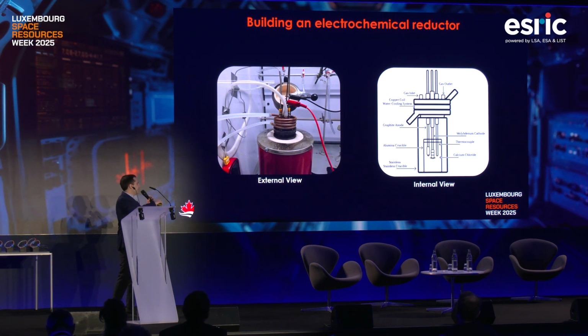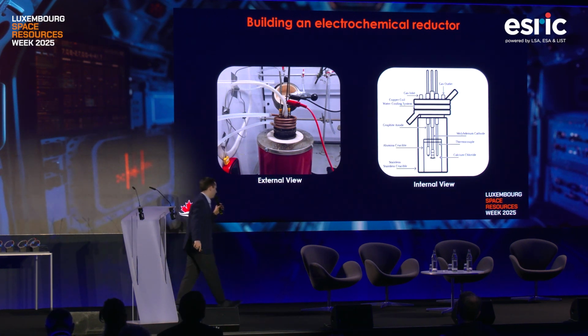In this case, our approach is based on the FFC process. As you can see, inside the reactor, we have calcium chloride here. This would be our electrolyte. Then we have our different electrodes. In this case, as a first demonstration, we were using a graphite anode. But as it has been discussed, if we were to use an inert electrode instead of graphite, we could extract oxygen.